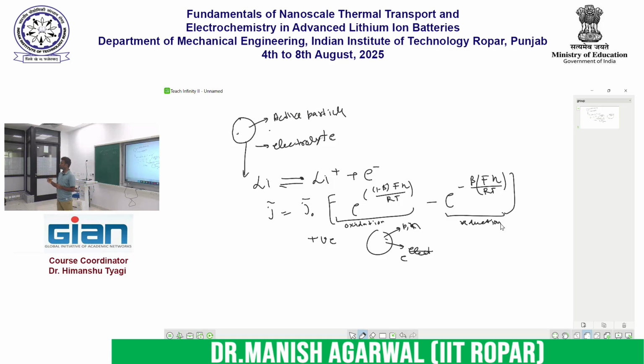In most cases you will see the beta value taken as 0.5. That is quite standard, unless, very rarely, some other value is taken. F is the Faraday constant, and eta is known as the overpotential. The overpotential is phi k minus phi e minus the open circuit voltage of that particular electrode at that particular concentration, right?